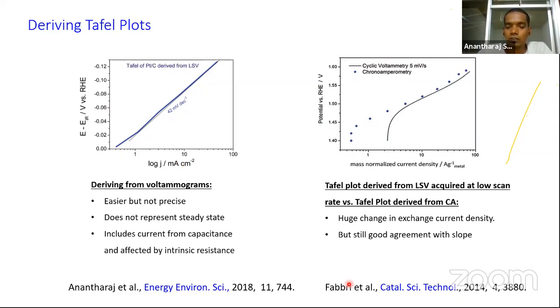This was shown by Fabbri et al. in an important report in 2014, where they studied the difference between the Tafel lines obtained with chronoamperometry and the ones obtained with cyclic voltammetry at 5 millivolt per second. In the linear region where we measure the Tafel slope, there is no apparent difference. But as you can see, the exchange current density, which is obtained by extrapolating this linear region, can be highly different from one another. So there is a big difference. You cannot rely on the Tafel plot that you obtain by replotting voltammetry, even at a very low scan rate, for accurately calculating exchange current density.